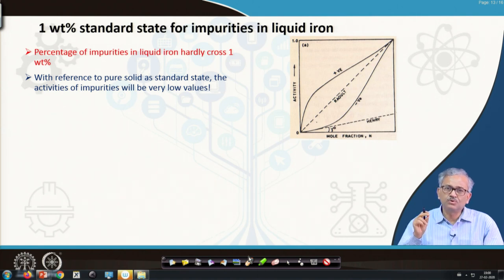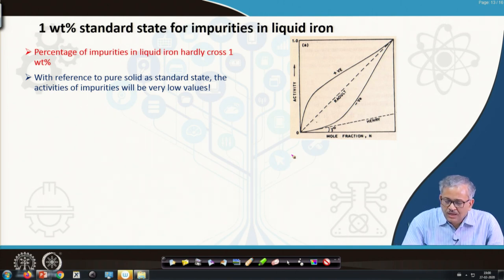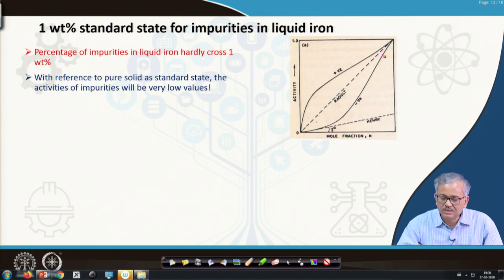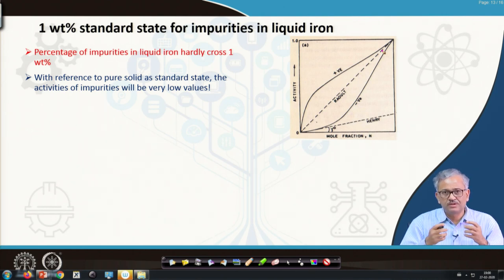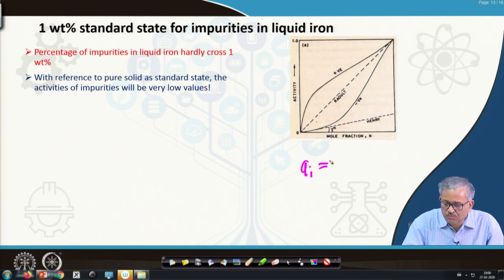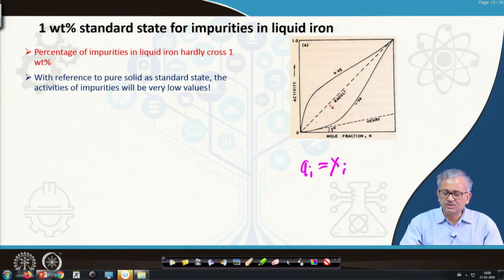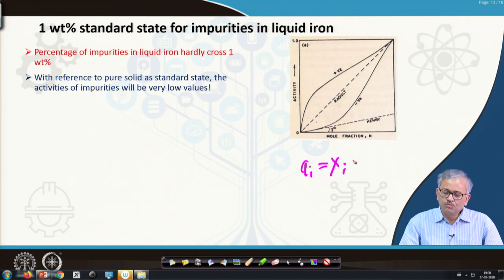Activity does not have any absolute value; it is always expressed relative to some reference. Here the reference is pure solid as the standard state. If the solid or liquid is pure, we assign activity equal to 1. For an ideal system with no interaction between solute and solvent, Raoult's law is valid, and activity equals mole fraction. So when xi equals 1, activity equals 1 — that is the pure solid at the standard state.